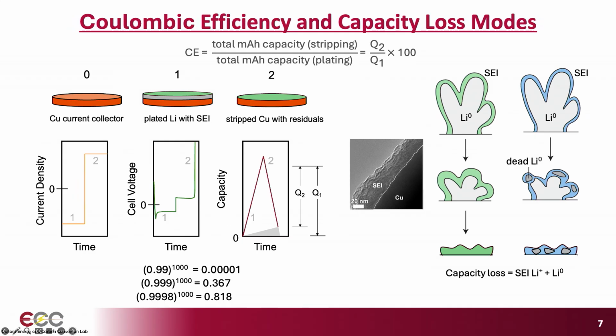So where is the field today? We're starting to see more and more electrolytes that can get around 99.6, 99.7, occasionally 99.9, but usually the 99.9 is not over 1,000 cycles, and we see degradation. So in some ways, we've never been this close, and in some ways, we're still really, really far. And so we really have to get this exactingly right. So our margin of error here is this 0.02%.